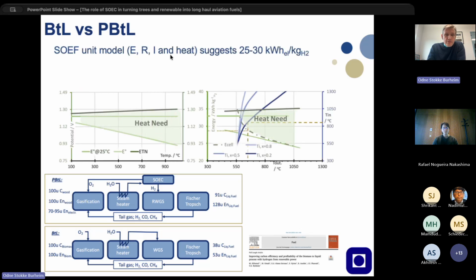In doing this, we have done a little bit of modeling of the cell potential of solid oxides. We have also looked at heat integration. If you preheat steam, and there's quite a lot of high temperature heat from the gasification, we can envision lowering the cell potential of the solid electrolyzer, balancing out the ohmic losses, and therefore have very high energy efficiencies.